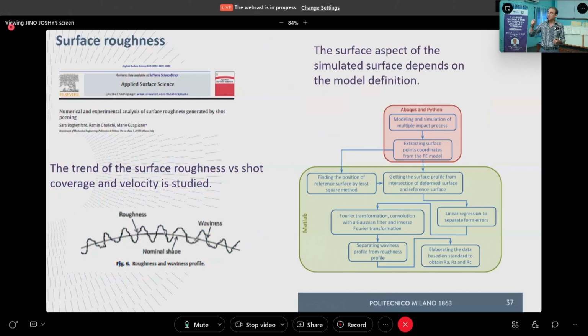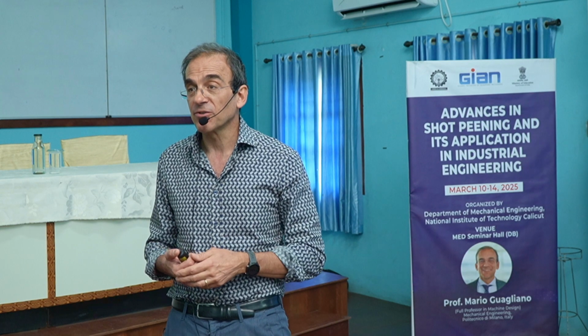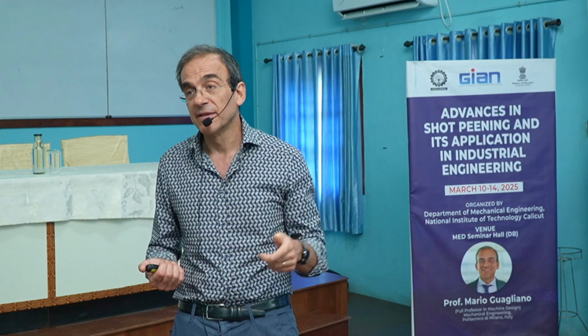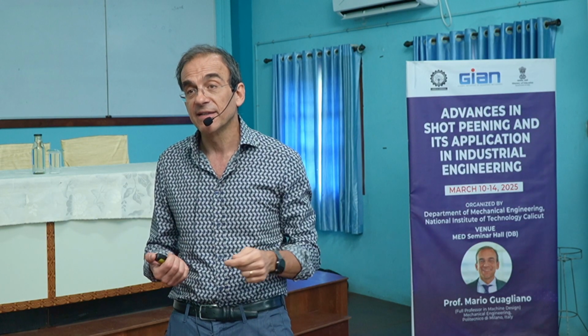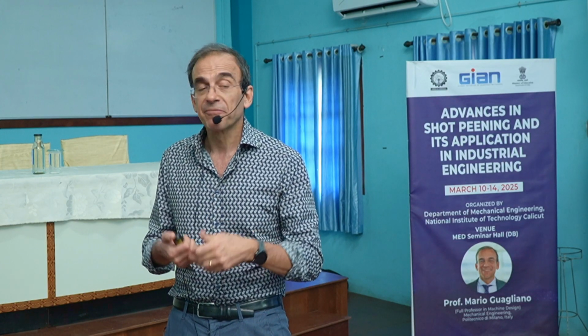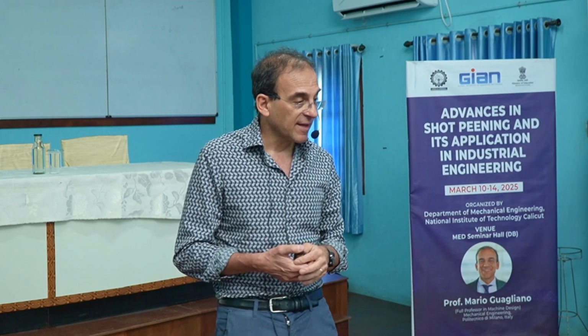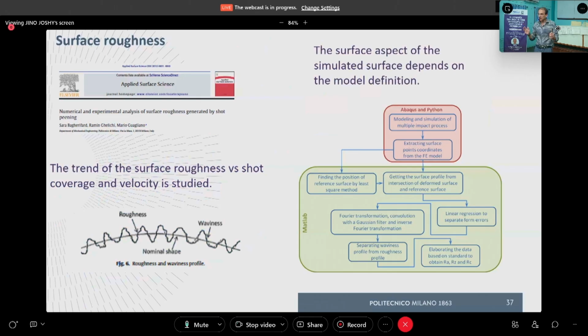Because why? Because when we perform a finite element analysis, the surface deformation is related to shot peening, to the physical parameters, but also to the choices we have made in terms of finite element simulation, the finite element model. Indeed, we have different kinds of finite elements, with linear shape function or with parabolic shape function, and the deformed shape, especially at small scale level, will be affected by the type of element we are using, by the density of the mesh we are using, and so on. So the use of the finite element result in terms of displacement and displaced surfaces is not enough, but we need to have an accurate estimation.